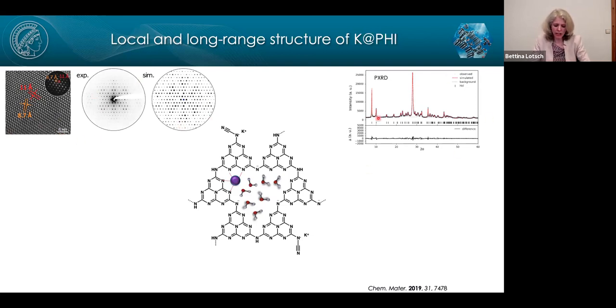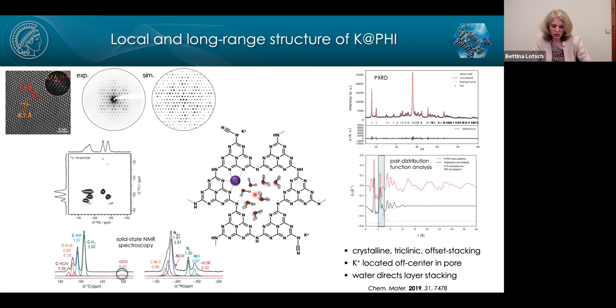Combining with powder X-ray diffraction, we came up with a structure model that shows us it is a 2D heptazine-based system, but not only heptazine-based. As you've probably spotted already, we have alkali metal ions, here potassium, sitting in the pores, and these alkali metal ions are hydrated. Local structure analysis, pair distribution function analysis, and also solid-state NMR tell us that this potassium ion is not sitting in the center of the pore, but is offset towards the carbon nitride backbone. So there's likely an interaction with the carbon nitride backbone. And we have a lot of diffuse electron density in the pore. So it's a highly hydrated system.